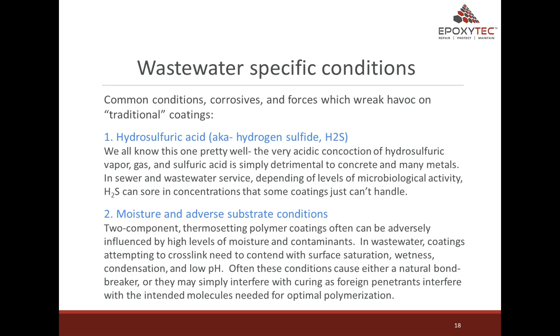Common conditions, corrosives, and forces which wreak havoc on traditional coatings. Number one, hydrogen sulfide, aka H2S gas. We all know this one pretty well. The very acidic concoction of hydrogen sulfide vapor, gas, and sulfuric acid is simply detrimental to concrete and many metals. In sewer and wastewater service, depending on levels of microbiological activity, H2S can soar in concentrations that some coatings just can't handle. Secondly, moisture and adverse substrate conditions.